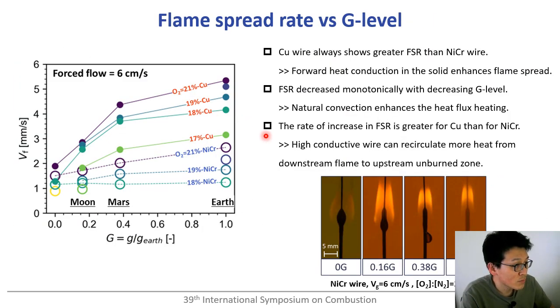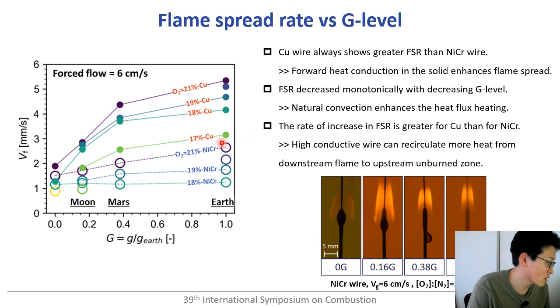So this slide shows the measured flame spread rate as a function of gravity level. As shown in this figure, gravity changed the flame spread rate significantly. In the figure, the filled circle symbols are data for copper wires and open circles are data for nichrome wires. Different colors indicate different oxygen concentrations. As you can see, as oxygen concentration increases, spread rate increases. And as for the effect of core material on the spread rate, the copper wire always shows a greater spread rate than nichrome wire. This means heat conduction in the solid phase can enhance the flame spread rate.